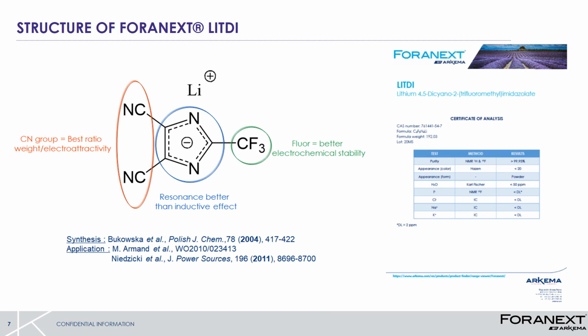Our other salt, the LiTDI, the structure of this salt has been well designed to improve the battery performance. In fact, the aromatic part allows to increase the charge separation between the lithium cation and the anion, and also brings high chemical stability. The CF3 group allows a good electrochemical stability, and the cyano group allows to decrease the interaction between the anion and the lithium cation, but also allows to well passivate the aluminium and to trap water and Lewis acid formed during the cycle life into the electrolyte.